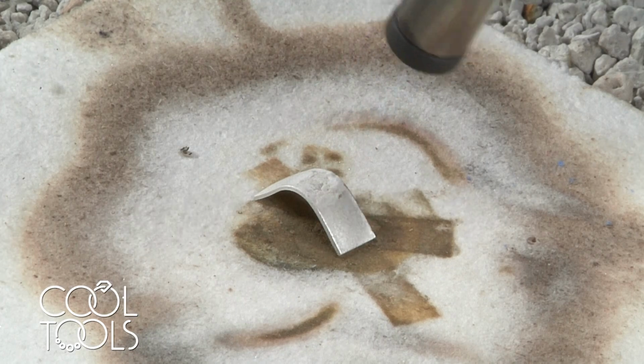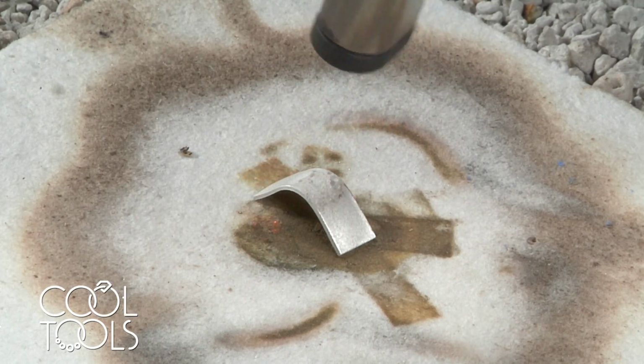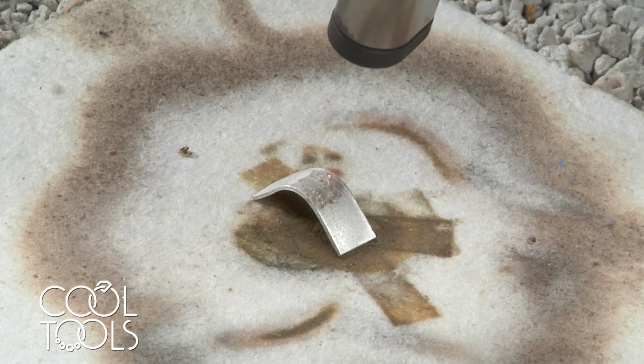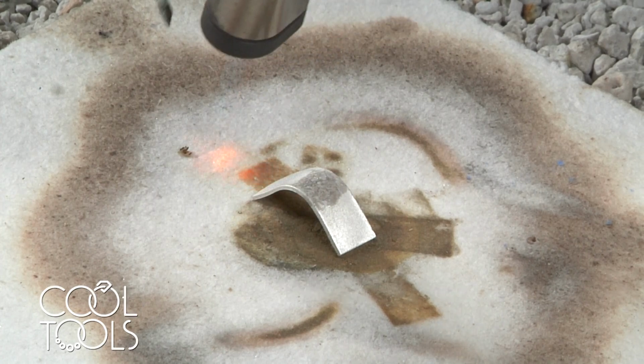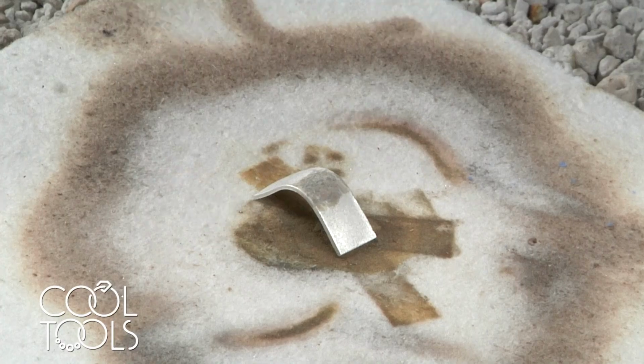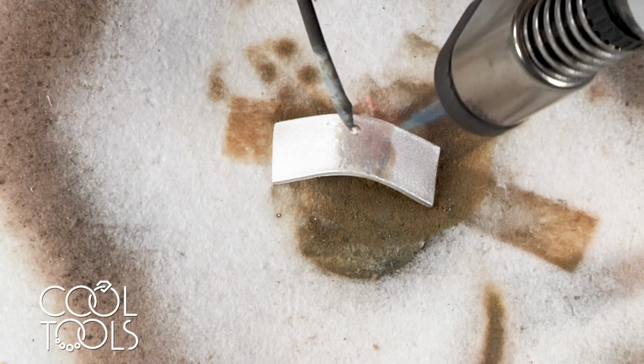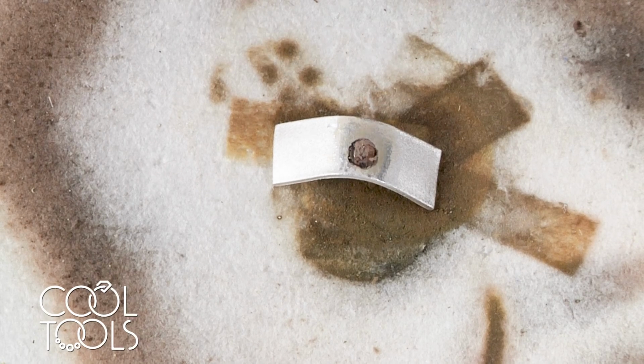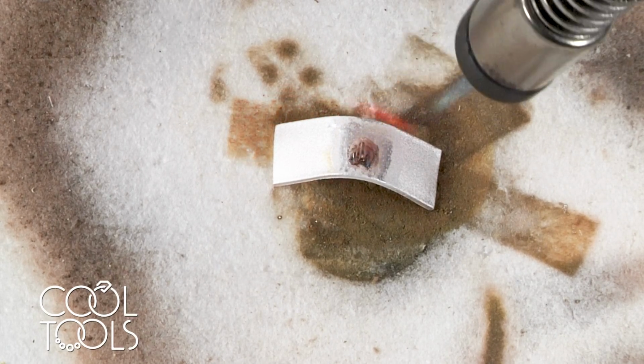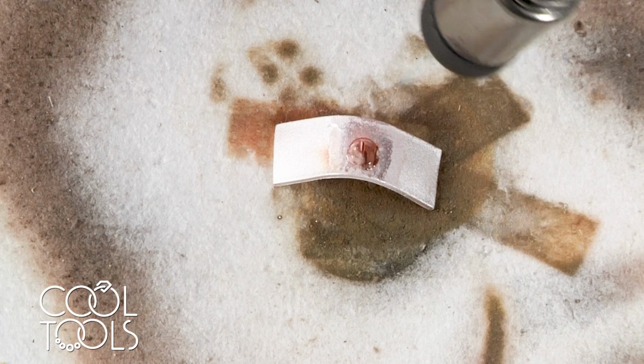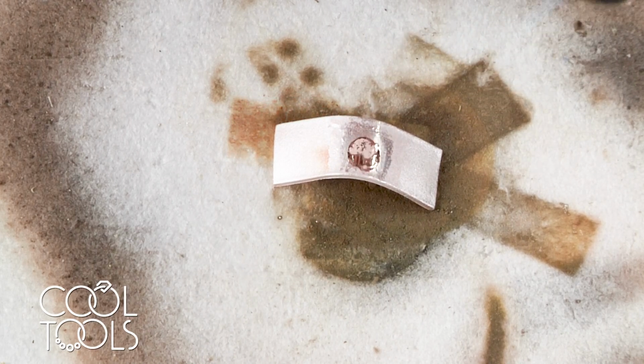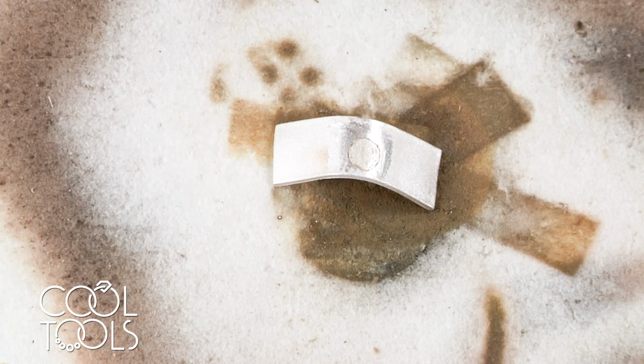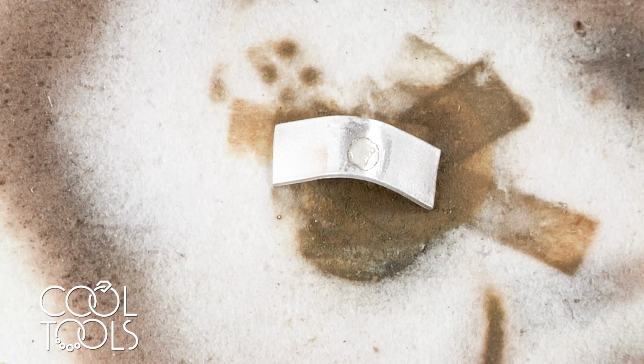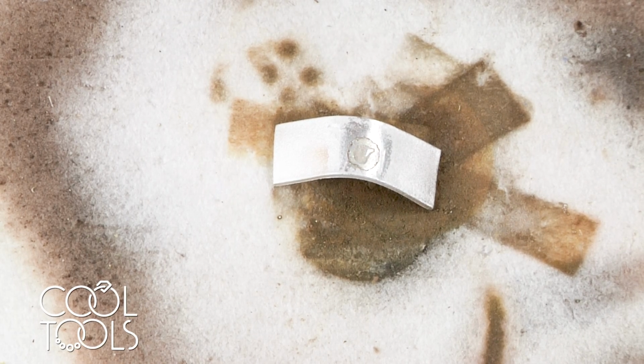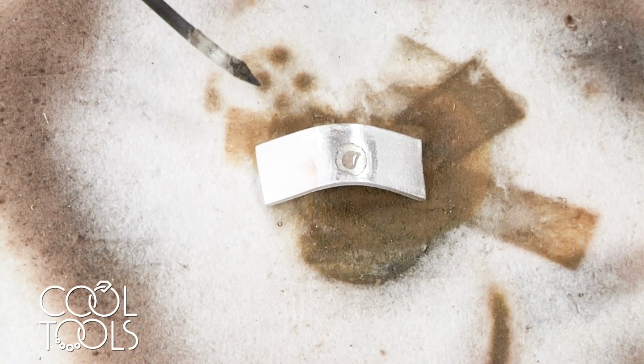Over here, preheating my metal in that flux. Make it nice and sticky. And then this is 3 little chips of solder. And move it over to my clay. And you can see it flowing on the surface there and spreading out because this whole piece is hot, but it's not going anywhere. It's not soaking in. And this clay was just torch fired. It didn't have the extra long soak at 1650, and it still is doing a really good job not soaking solder. So I'm really excited about that.